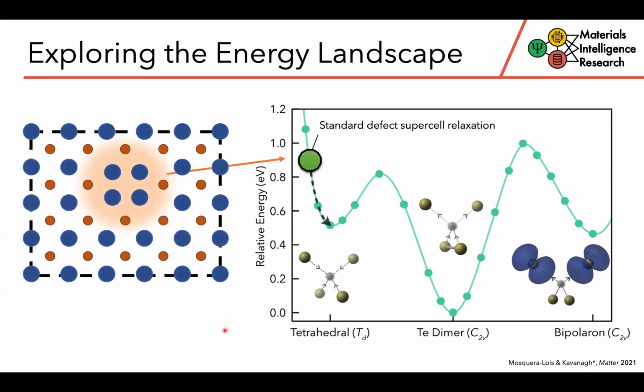Okay. So one of the issues with this approach, however, and something that I've looked at quite a bit in my research, is the fact that when we create our initial defect structure in this way, so the very simple approach of just removing an atom to create a vacancy or adding an atom to create an interstitial, there's no guarantee that when we do this gradient-based energy relaxation, that we'll actually end up with the ground state geometry. So if we have something like this, where on our defect structural potential energy surface here, so here where y is energy and our x-axis is some structural coordinate, often we might actually be closer to this local minimum on the potential energy surface, so that when we do this ionic geometry optimization, we end up in this local minimum, or essentially a metastable structure, which may not reflect the true defect behavior.